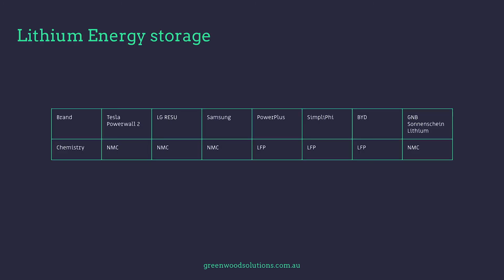Now this little table shows some major brands out there and what kind of chemistry they're using. You can see very quickly that NMC seems to be the chemistry of choice for the Tesla product, LG, Samsung and Sonnenschein. Whereas PowerPlus, Simplify and BYD use the safer lithium iron phosphate solution. The most exciting battery at the moment from the lithium stable is lithium titanate, with really good longevity on life. There are some really good attributes, but it's very expensive, though that can change quickly.